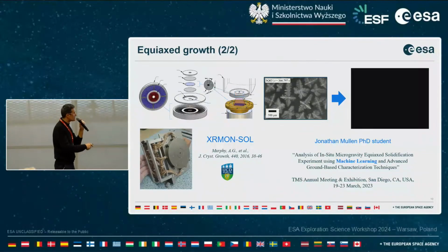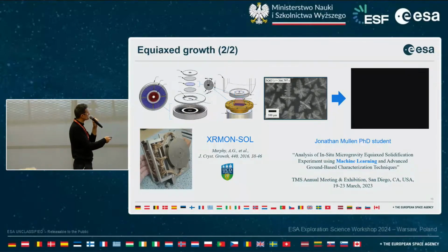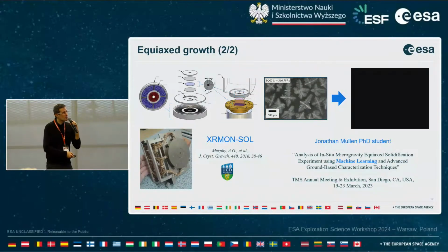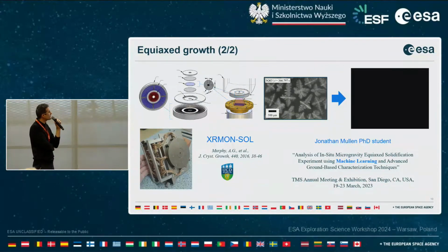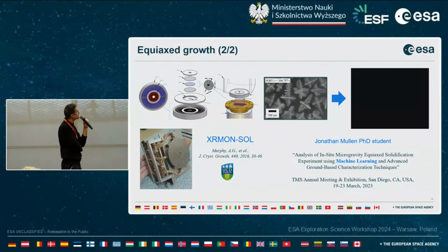And second part on equiaxed growth, I would like to mention works this time carried out by our colleague at UCD in Dublin, who also studied equiaxed growth in an aluminum-copper alloy using the so-called solidification device, which was developed for the MASER 13 sounding rocket experiments. So the experiments are quite old, but the analysis is still in progress. And here you can see a picture recorded during the microgravity experiments.